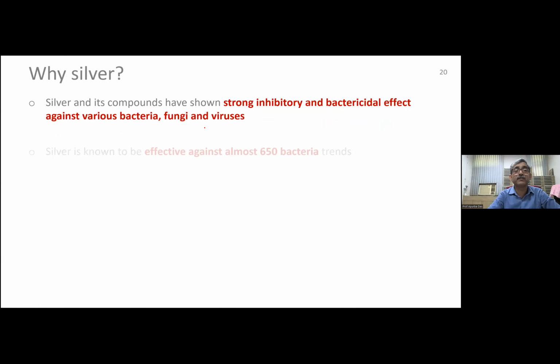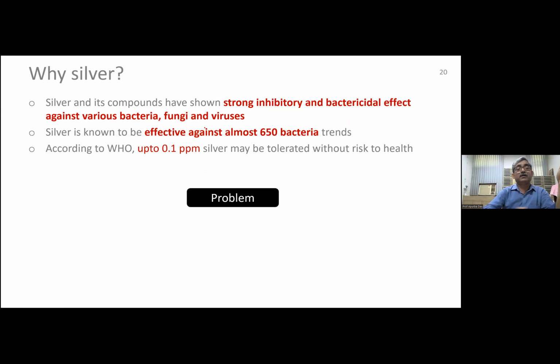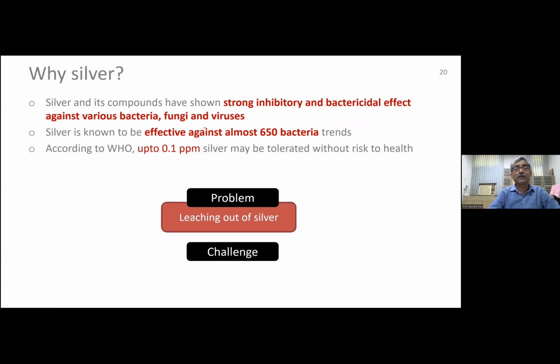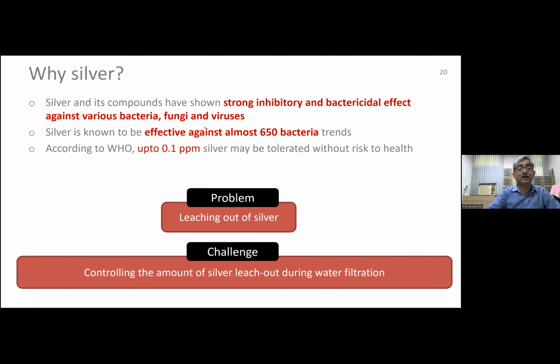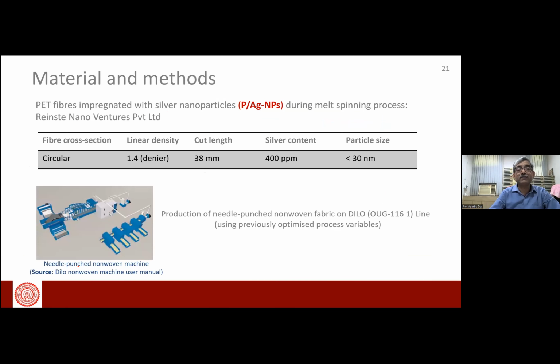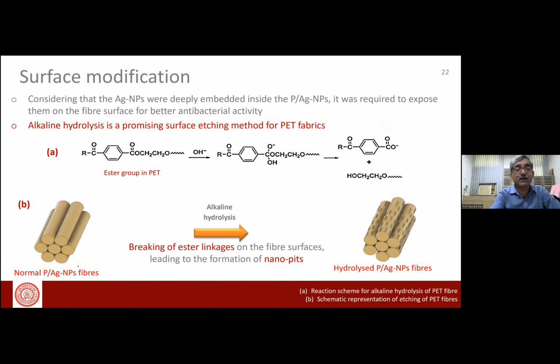The silver nanoparticle is very well known as an antibacterial agent, so I am not going in depth. So what we have observed, this is the normal polyester silver nanoparticle fiber, where you will see most of the nanoparticles are actually inside the structure. So we have to expose this nanoparticle to the surface so that it is very much active.